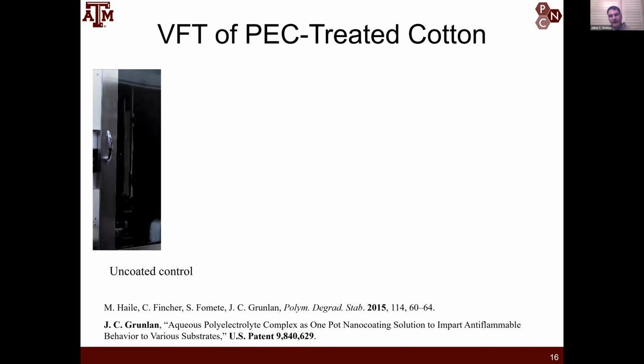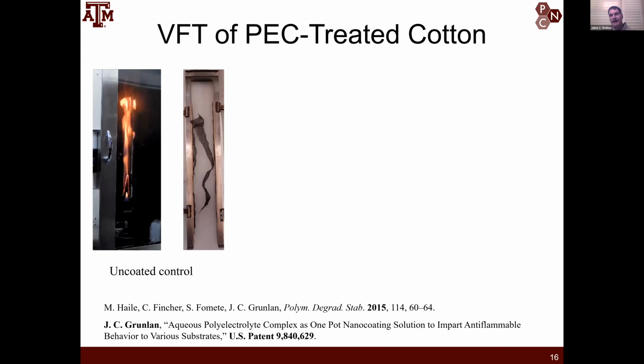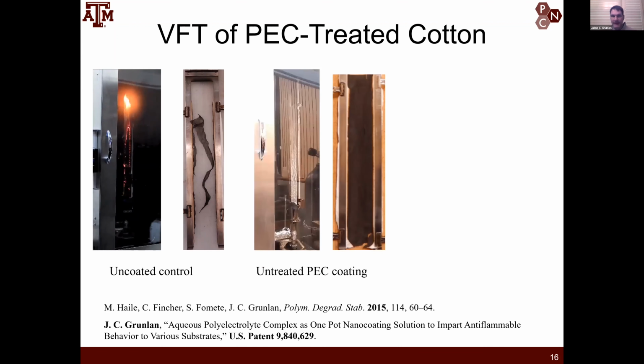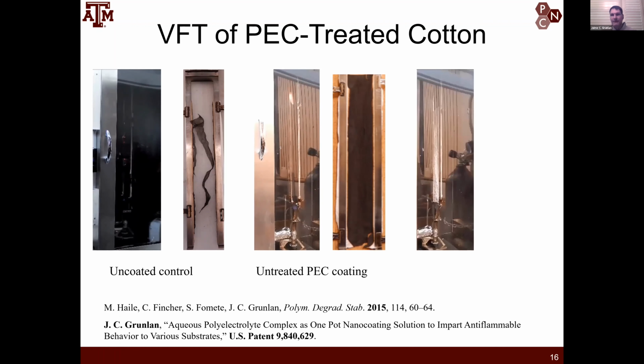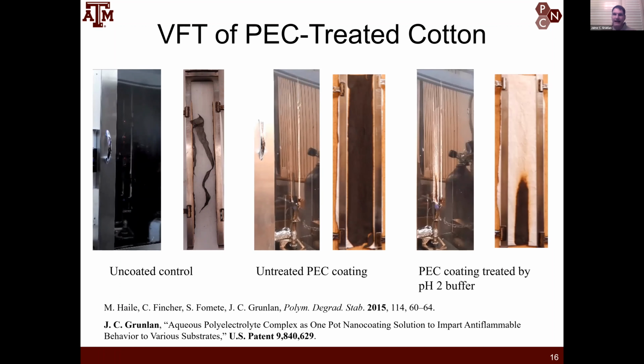And then, if we take a look at the uncoated cotton, of course, this is a vertical flame test that I'm showing. ASTM D6413 is the standard vertical flame test. Cotton is completely consumed, of course, by the fire without any treatment. If I apply my polyelectrolyte complex, but I don't use the buffer to lock in that complex on the textile, I'll get a lot of char, but this is not considered a passing vertical burn test. But then once I cure, we call it curing with the buffer, when I lower that pH, I get a highly ionically cross-linked conformal coating on the cotton, and then we pass the vertical burn test.